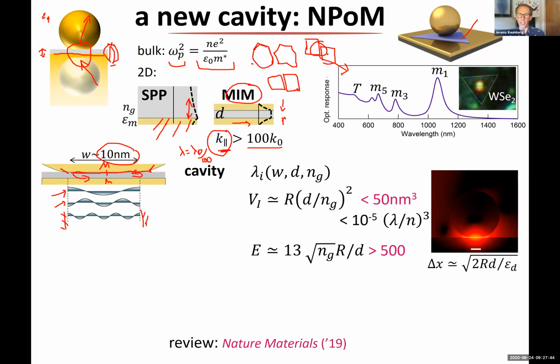You can actually do a very nice model, which is based on the capacitance of this gap. It's an optical capacitance, and it just depends on this area. And as I'll show here, that's why the facet matters. So this is an experimental issue, but in principle, if one could make perfect... Yeah, no, it'd be completely fine. If one could, yeah, but we've tried that for a long time. If one could beautifully control this, it would be just as good as the nanoparticle on a mirror.